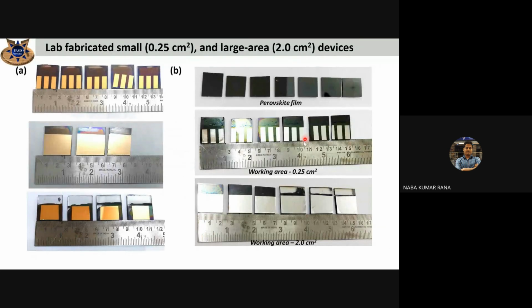And these are our lab fabricated devices. This is a small area gold electrode based device, so we used gold as the top electrode, and this is a single cell large area device. And this is a silver electrode based device, where we used silver as the top contact electrode because it is a cost effective electrode, in both small area and large area devices. We fabricated these films inside an inert atmosphere, that is a glove box. We use the inert atmosphere for deposition of the perovskite film because perovskite is very moisture sensitive, so it can easily degrade outside in the ambient atmosphere.